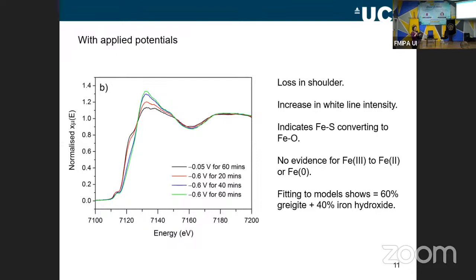And both of those features together tell us that FeS bonding is converting to FeO bonding, so it's turning into an oxide. What we don't see happening is that iron 3 is being reduced to iron 2 or iron 0, because if that was the case, this spectrum would all shift, it would all move position, and it doesn't, it's in the same place. So only the shape changes. And if we fit this to model compounds, this tells us that the material we end up with is 60% greigite, so the original, and 40% some type of iron hydroxide species.